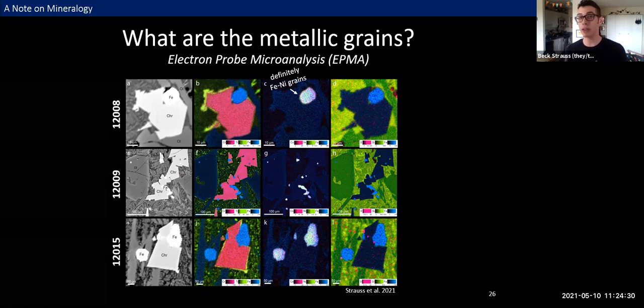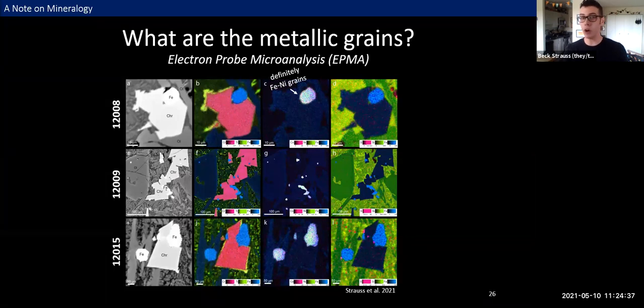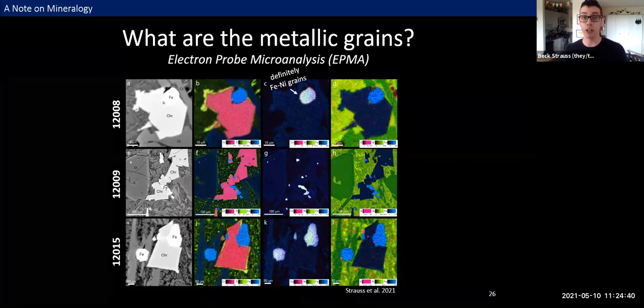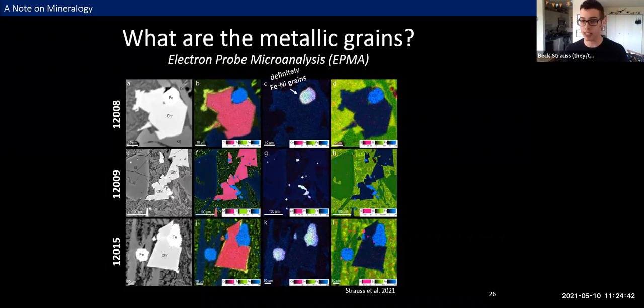In fact, we mostly found martensite, where studies of other samples from similar parts of the Apollo suite have found predominantly kamacite. We also noticed that many of those iron nickel grains are not homogeneous, and you can actually see it in these figures. You can kind of make out some compositional gradients along this top grain and also on this lower one where there's more nickel to one side. We also observed some bright submicron scale grains that were unfortunately too small for us to acquire quantitative points from. But mainly what we can take away from this is that we observed multiple sizes of both kamacite and martensite,